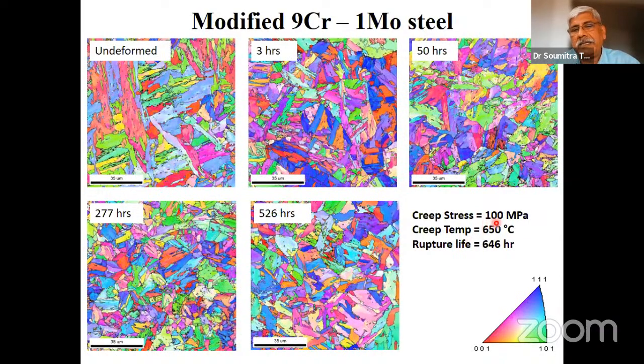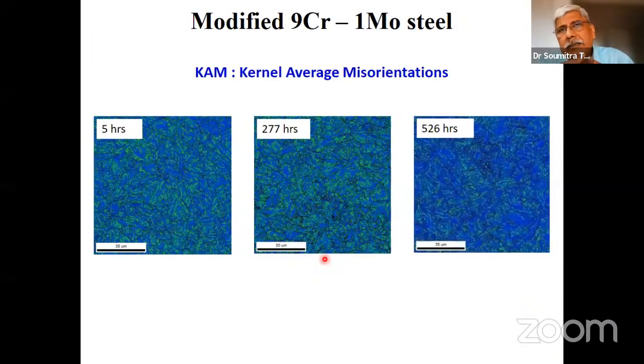This was creep tested at 100 MPa at 650 degrees centigrade, which is typical for this type of material, maybe at higher stress levels. But when you look at the type of dislocation substructure that is there through what is known as kernel average misorientation, because these dislocation substructures within a grain cause slight misorientations from one part of the grain to the next part of the grain, etc.